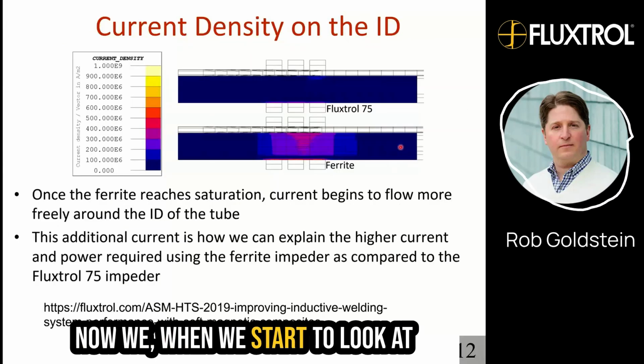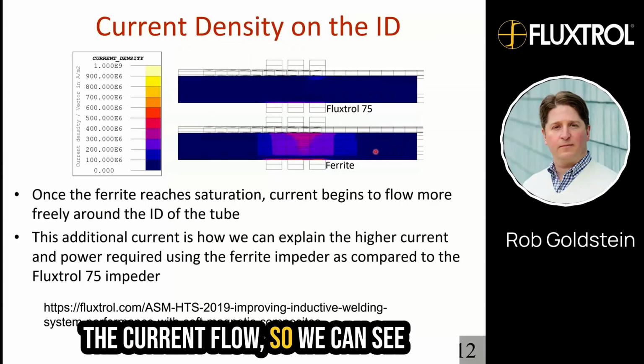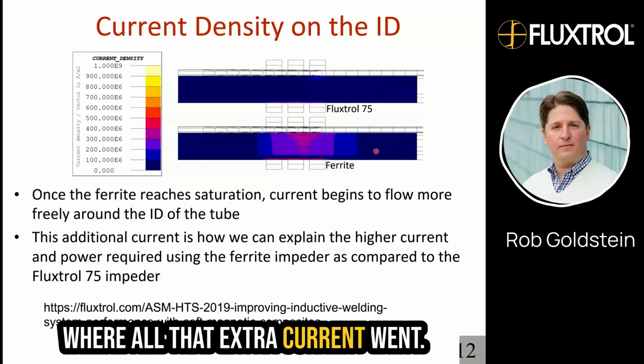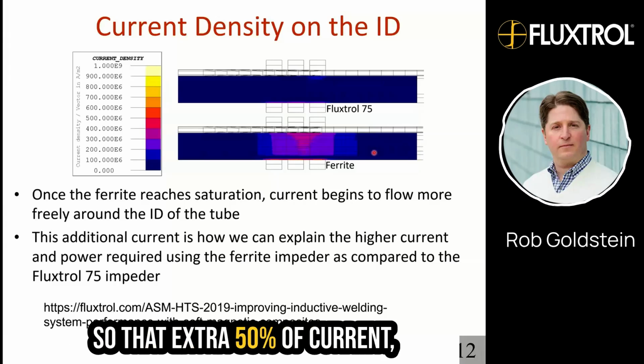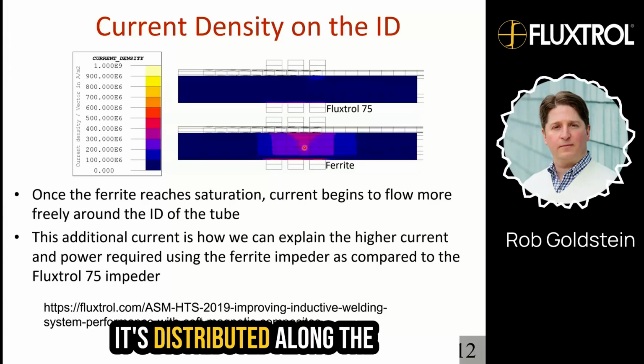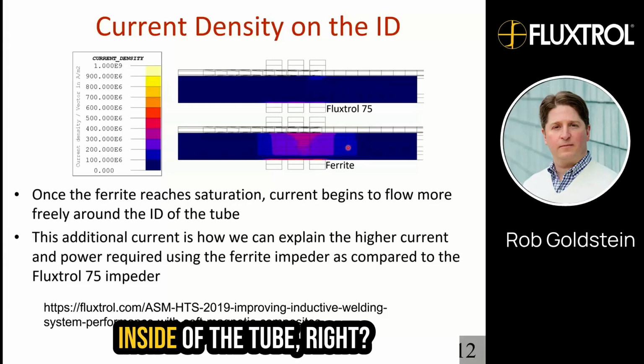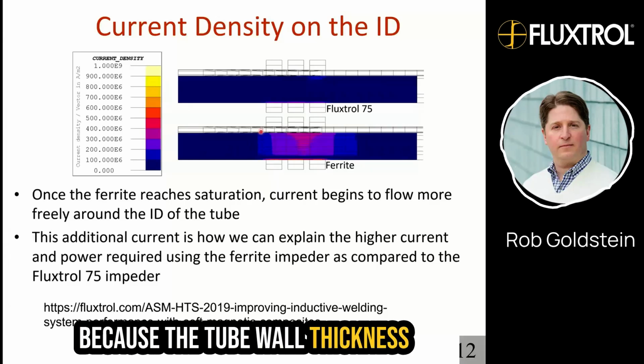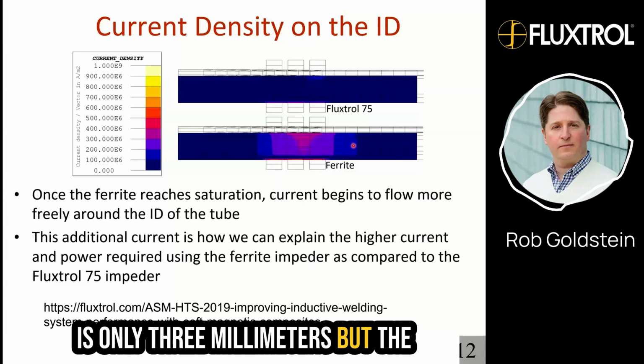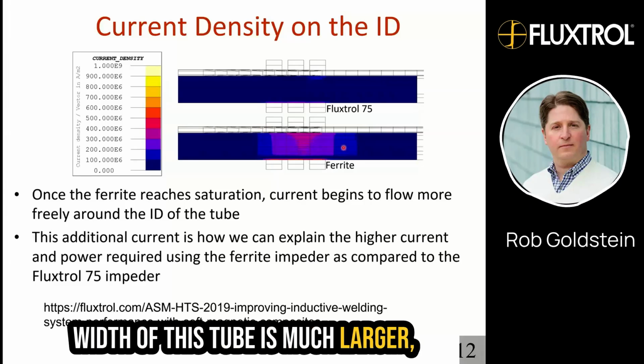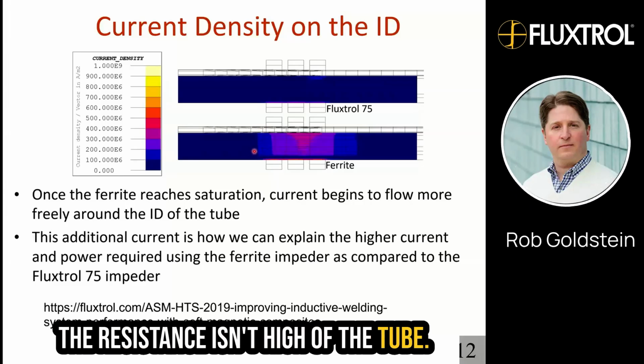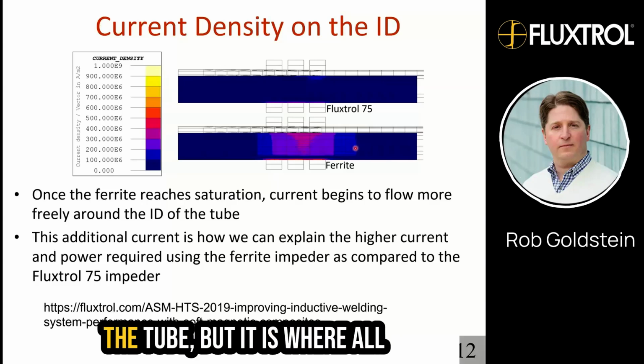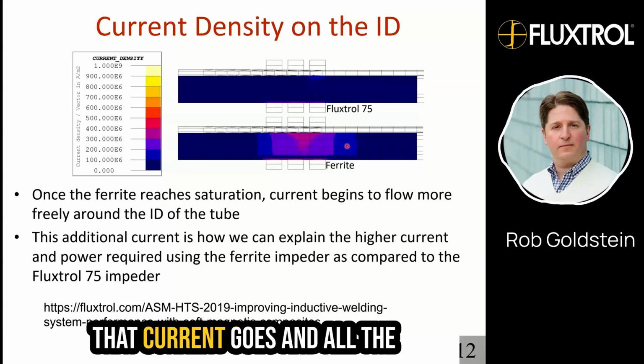Now when we start to look at the current flow, we can see where all that extra current went. That extra 50% of current is distributed along the inside of the tube, right? Because the tube wall thickness is only 3 millimeters, but the width of this tube is much larger, the resistance of the tube isn't high. It's not huge levels of loss in the tube, but it is where all that current goes.